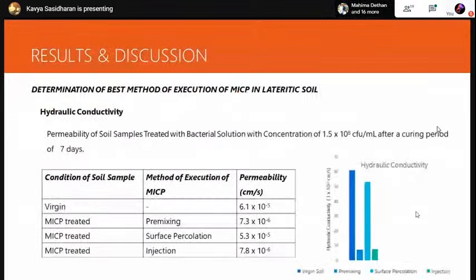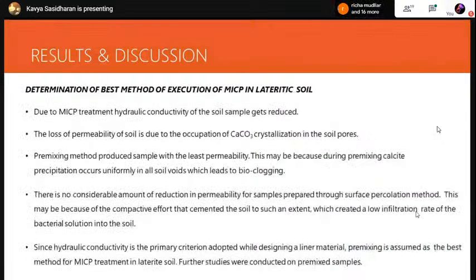So coming to the results, first of all, determination of the best method of execution of MICP in lateritic soil. The hydraulic conductivity of soil was checked, and it was found that the hydraulic conductivity of soil reduced with the MICP treatment, and it was least for soil treated by the premixing method. The premixing method produced the least permeability. This may be because during premixing, calcite precipitation occurs uniformly in all soil voids, which leads to bioclogging.